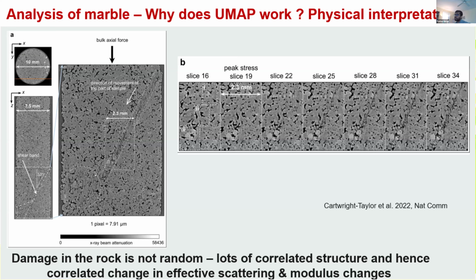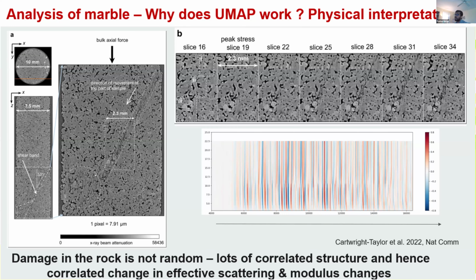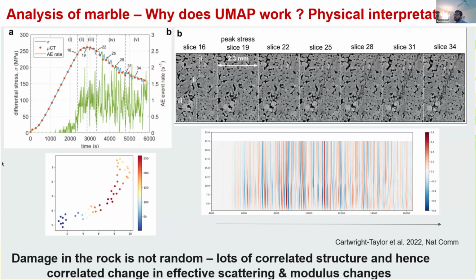And even in this particular experiment, we looked at some of their active waveform data where the tomography was being done. What we found was actually UMAP does a very good job. So if we show the figure on the left, the bottom, that's showing the UMAP 1 and 2 dimensions for the active source for this particular data set. And then the color is showing the stress state. So the UMAP waveform features are distinguishing where you are with regards to stress relatively accurately.